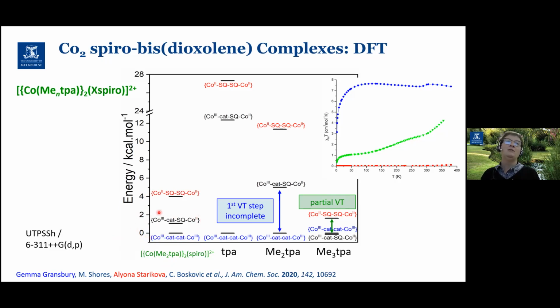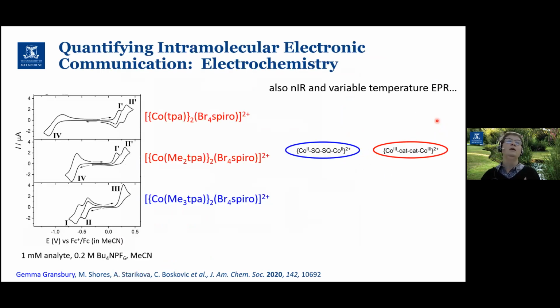Then you have the mixed valence state, and then you have the fully cobalt-2 semiquinone, all at accessible energies, and the mixed valence state is less than halfway between the energies of the two homovalent or homospin states. So exactly what you'd expect from what we know from spin crossover to see a two-step VT transition. So again, just finishing off with a bit of electrochemistry.